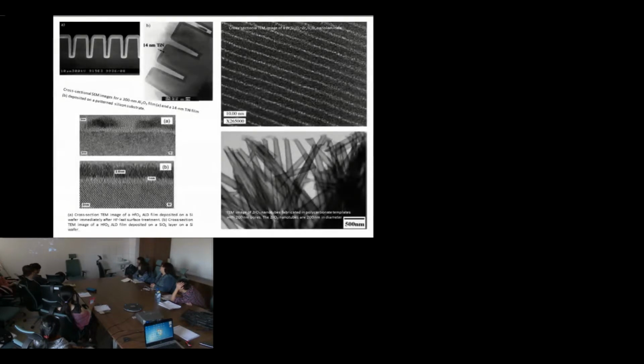So this is just a second. Yeah, it's this one. So at the very top left corner, you see that there was a substrate which was structured. So there were already some rows like nanowires, and the light covering you see here was made with atomic layer deposition. So you can really cover all the pores and holes in the sample with an atomic layer of some material, like you see that the layer is very uniform and it goes everywhere.